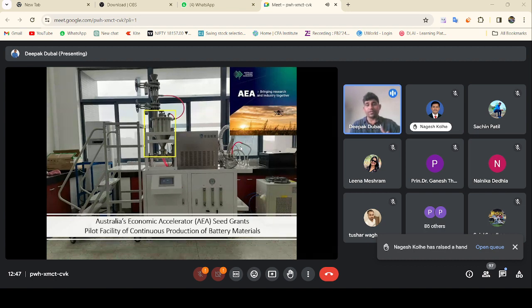In addition to that, this furnace is not a batch process, it's a continuous furnace. From one end, you can simply keep putting the material in, and at the end, you can just collect the product. The capacity of this furnace is 5 kilos per hour. So you can imagine if we run for 8 hours, we can generate almost 40 kilos of material per day. And we recently received funds for this battery project, one of the very big projects we received.